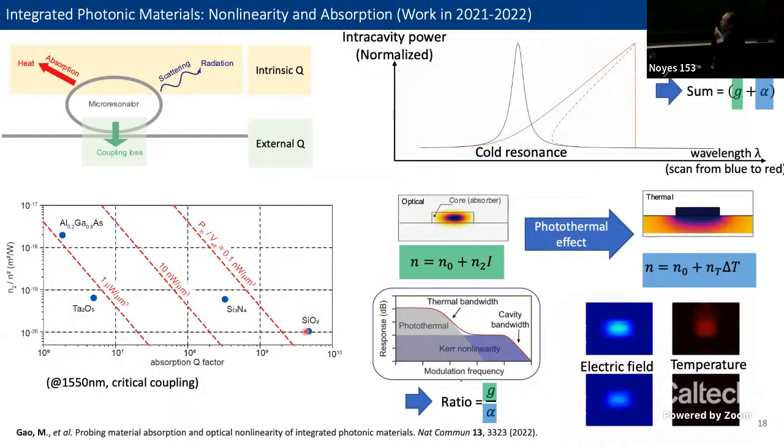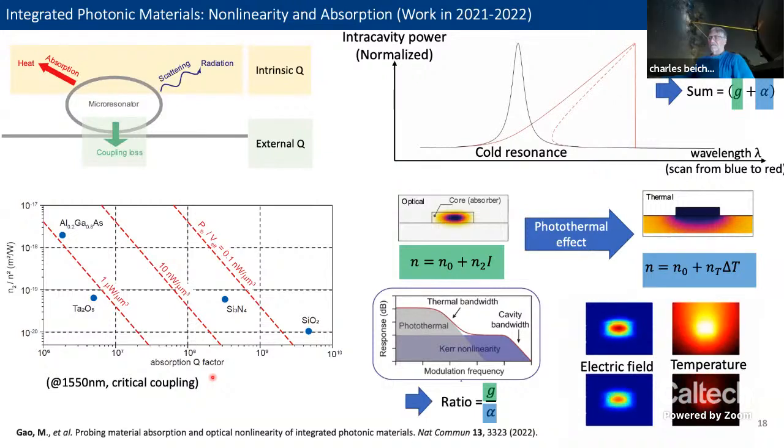So in that paper, we concluded that the OH absorption is a dominator in the current silica devices in the photonic engineering we are using. And that is Appendix D in my thesis as well. So Charles, hopefully this gives you a good answer. Yeah, thank you so much for that.